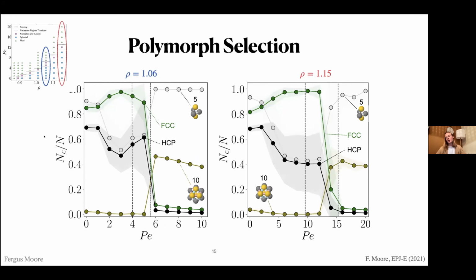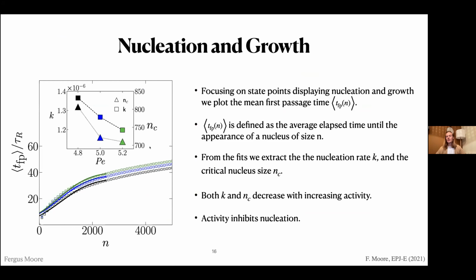So to look a little bit more into the nucleation and growth, we can see how these crystals nucleate as a function of activity. One way of looking at that is the mean first passage time, which is the time it takes for a crystal nucleus to reach a certain number of particles. I'm looking at three Peclet numbers in this case. The black is 4.8, blue is 5, and green is 5.2. On the x-axis, for 2,000 particles to join the crystal, it takes 30 for 4.8, and you can see it takes longer as you increase the activity.